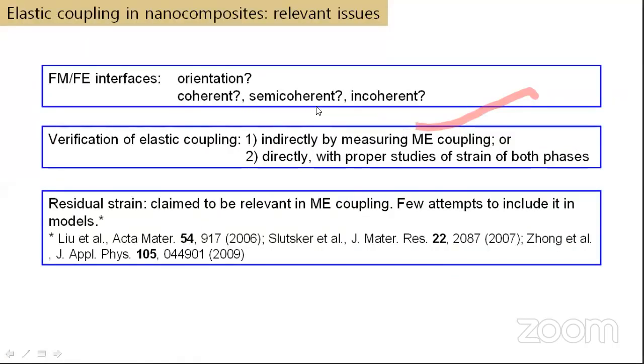So what are the parameters which are important to have these ferroelectric, ferromagnetic interfaces for the elastic coupling? One is the orientation, as I said before, and then whether the interface is coherent or semi-coherent. You can't have an incoherent one. Already I said these are all epitaxial films. If you have an incoherent interface, you will have amorphous material. So it should be either a coherent or a semi-coherent interface.